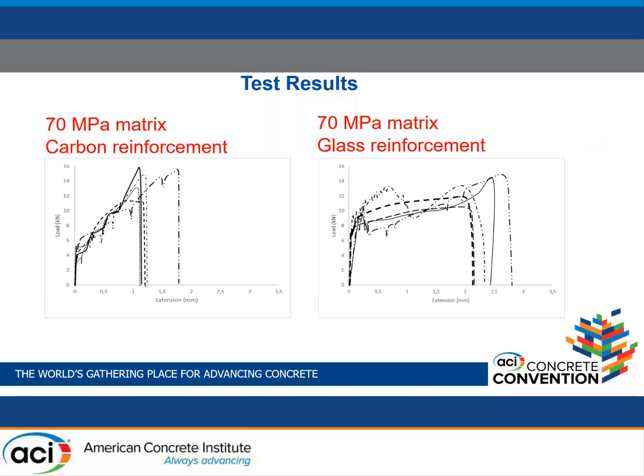In this slide, in the comparatively lower compressive strength matrix, the comparison of two fabrics is shown. Glass fabric reinforced matrix showed higher extension values. Carbon fabric reinforced matrix showed higher tensile loads than the glass fabric reinforced one. Here again, the slope of the cracked section is much higher for the carbon reinforced composite than the glass fabric reinforced one.